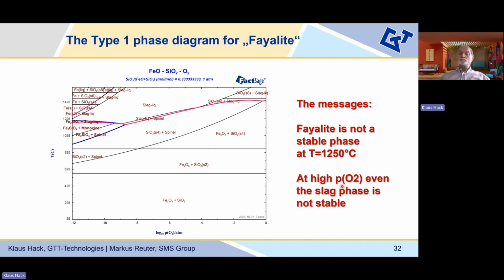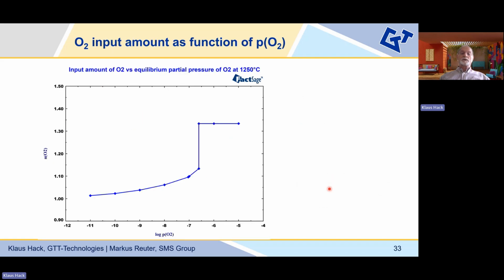And also the high oxygen partial pressure delivers a solid state even at high temperature. Now, if you look into the results of the calculation from Equilib, where you simply start with 2 iron and 1 SiO2, you fix the temperature to be 1250, and then you run the oxygen partial pressure through an interval,